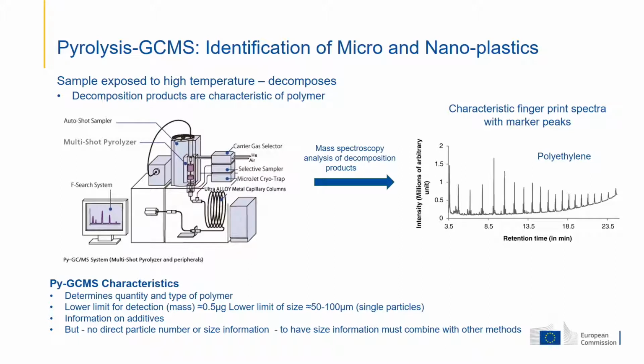This technique allows you to measure fairly small quantities of materials of the order of half a microgram, which corresponds to single particles about 50 to 100 microns. And it can also give information on additives, but unfortunately gives no information on particle size or size distribution.